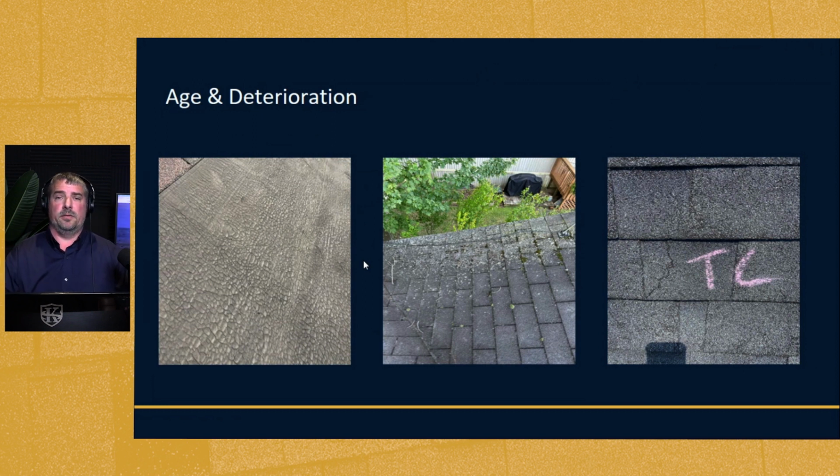Fun fact about lichen, if you don't already know, lichen can be very destructive to asphalt composition shingles. They actually feed on the ceramic granules of an asphalt composition shingle. And so whenever they finally die, deteriorate, and dry, they pop off of the shingle, and they leave these very nice circular blemishes that are very easily mistaken for hail impacts sometimes. So that's very important to understand.